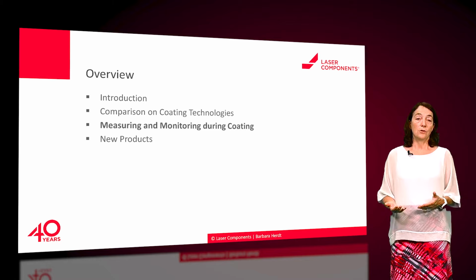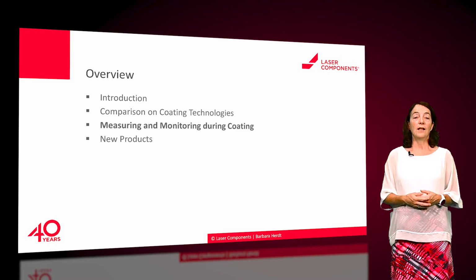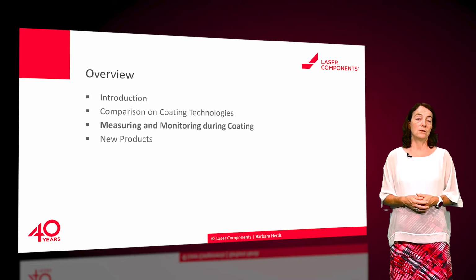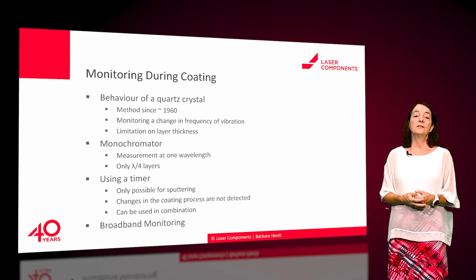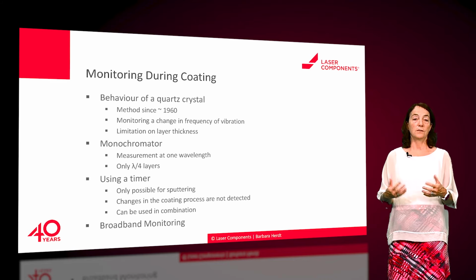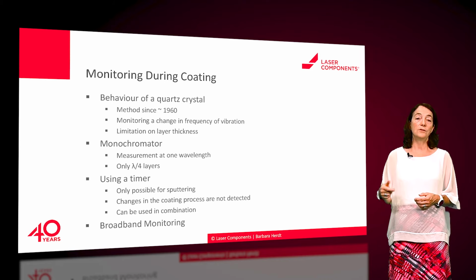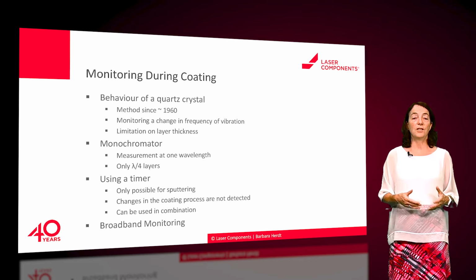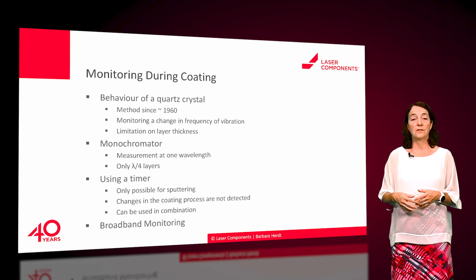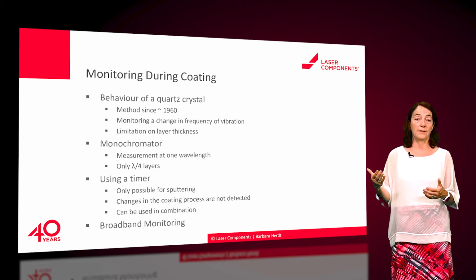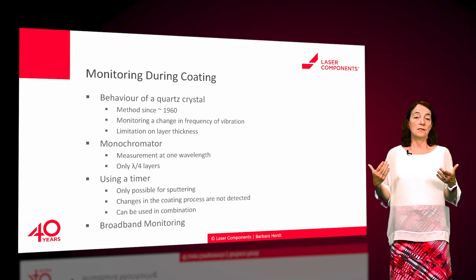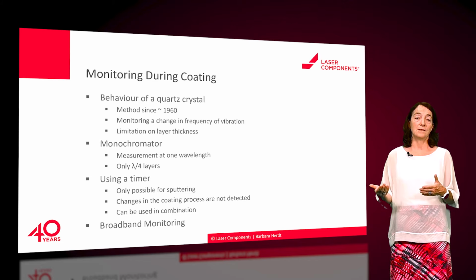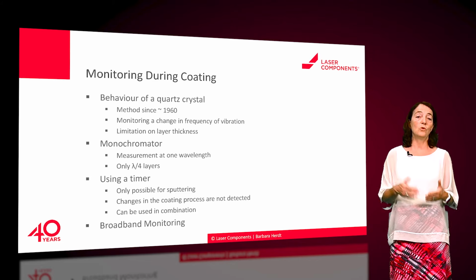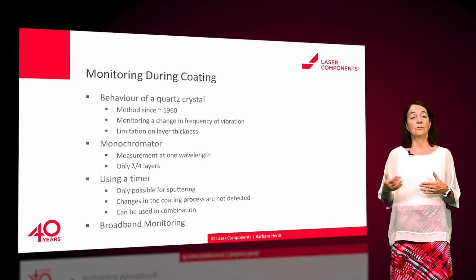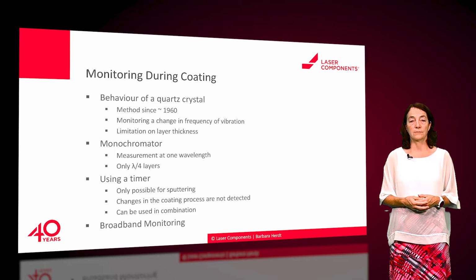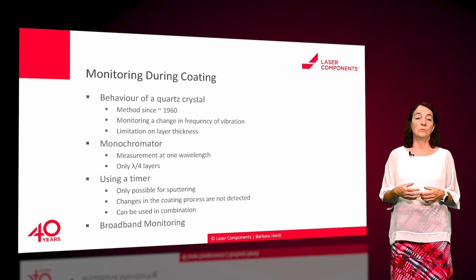Now you have heard a lot about the coating technologies, and I have mentioned the online measurement before. Let's have a deeper look into this topic now. The first and oldest monitoring of dielectric coating is the usage of a quartz crystal. The coating material is applied also on this crystal. The frequency of the vibration is changed due to material increase, so the vibration correlates to the layer thickness applied. This is a method which is used since the 60s, but limits the number of layers as the change of the frequency is getting less as more material is on the crystal, and then this is not good enough for high accurate optical coatings. Often coatings are monitored with a monochromator.